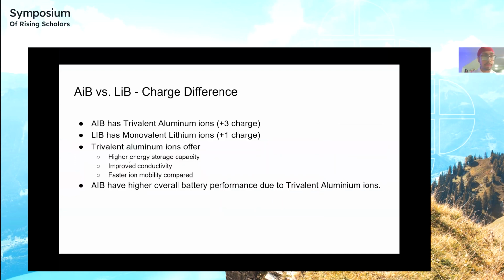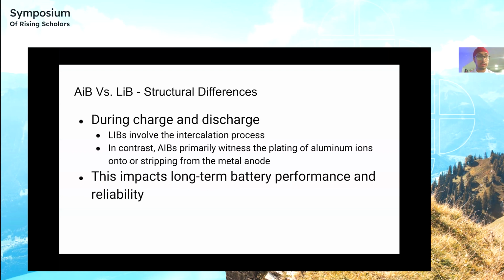All right, a few more differences. Aluminum-ion batteries have a trivalent aluminum ion, which has a +3 charge, whereas lithium has a +1 charge. Trivalent ions offer higher energy storage capacity, improved conductivity, and faster ion mobility. So, overall, AIBs have a better battery performance in this aspect. Let's talk about some structural differences too. During charge and discharge, LIBs involve the intercalation process, whereas AIBs primarily witness the plating of aluminum ions onto or stripping from the metal anode. This is one con in aluminum ions, as stripping and plating can degrade battery life.